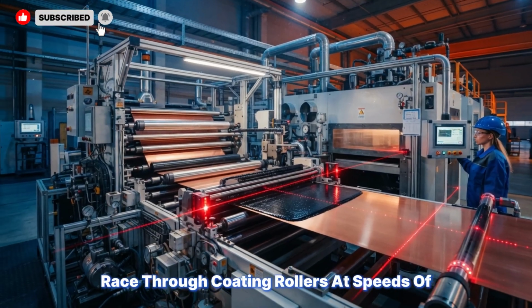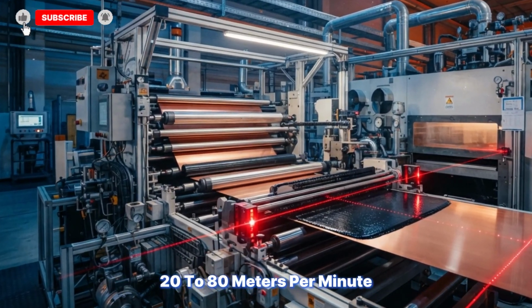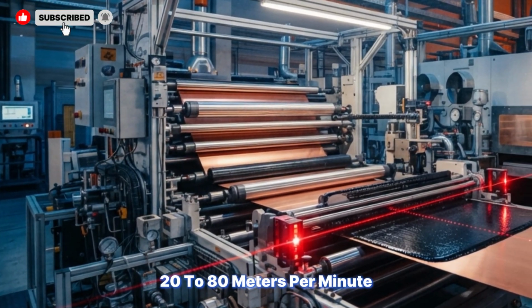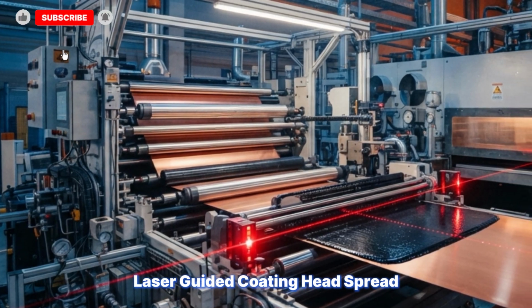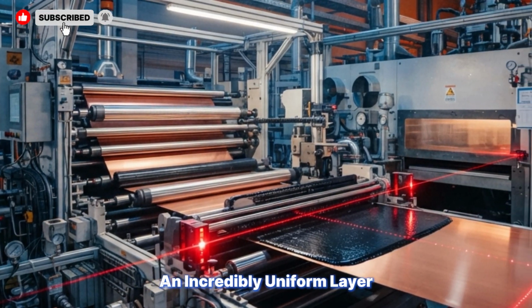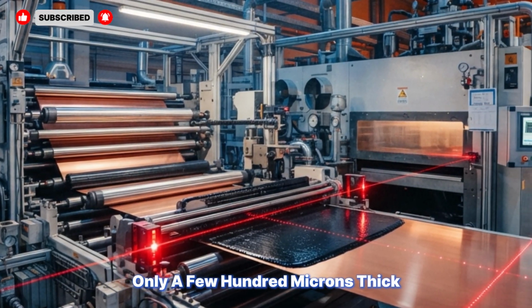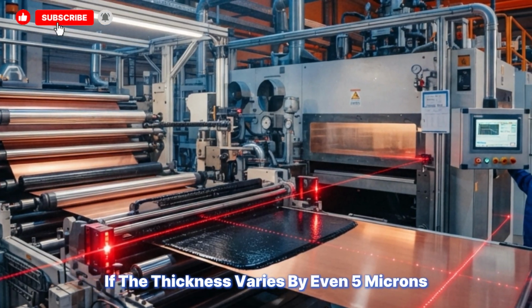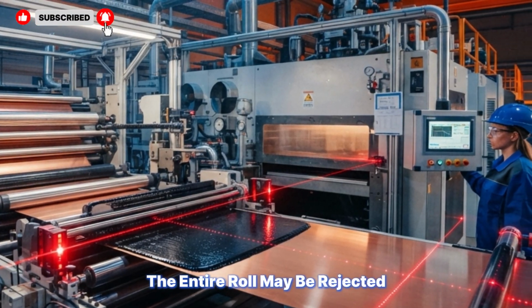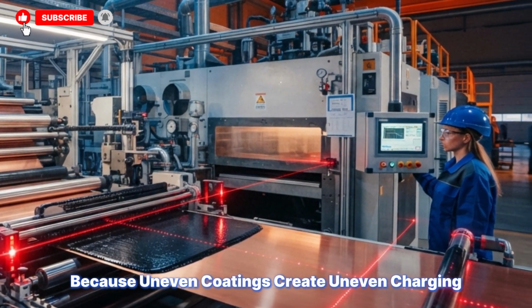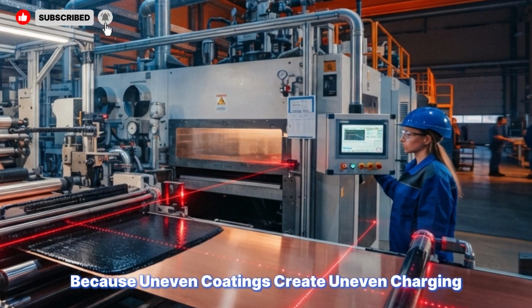cathode race through coating rollers at speeds of 20 to 80 meters per minute. Laser-guided coating heads spread an incredibly uniform layer only a few hundred microns thick. If the thickness varies by even 5 microns, the entire roll may be rejected because uneven coatings create uneven charging.